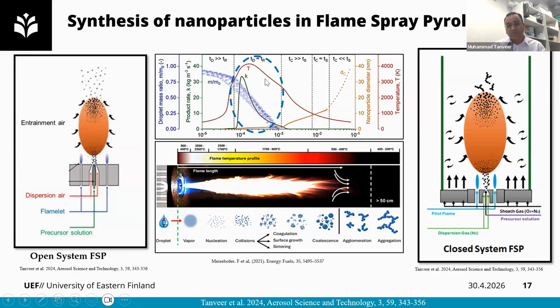Further downstream of the flame, the flame temperature decreases due to entrainment of air, or due to less availability of precursor there. The particle starts to grow, and its primary particle size grows up to a certain nanometer size. Then when the flame is quite cold and the particles are exposed to room temperature, they start to aggregate and agglomerate. So this orange line shows the different particle size evolution stages of the carbon nanostructures. Here we can see how the mechanism of particle formation of nanostructures happens in closed flame pyrolysis. When xylene, because we have used xylene as the precursor for the synthesis of carbon dots,